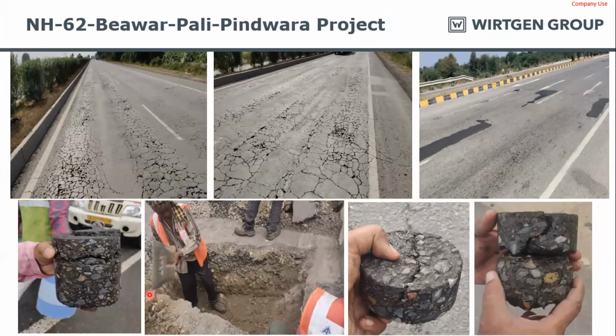This is one more project, NH62, Beawar Pali Pindwara. This was executed by L&T. These are some of the field investigations which were done. We dug test pits. A total of 6 pits, measuring 1.2 meters, were dug up to the subgrade level at 6 different locations of this job site. Then coating of bitumen mix was done to evaluate the depth of the crack up to which the asphalt layer is damaged. Then we collected the milled material for evaluation of the mix design in the laboratory. Various laboratory tests were done, and then the project was executed.